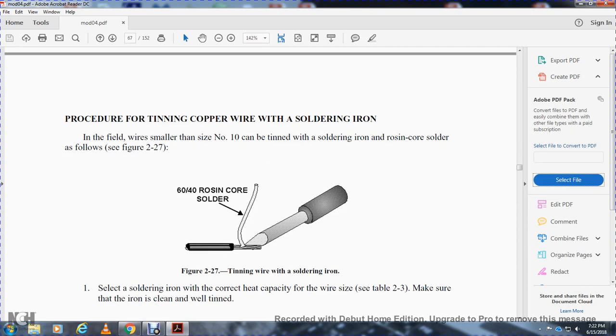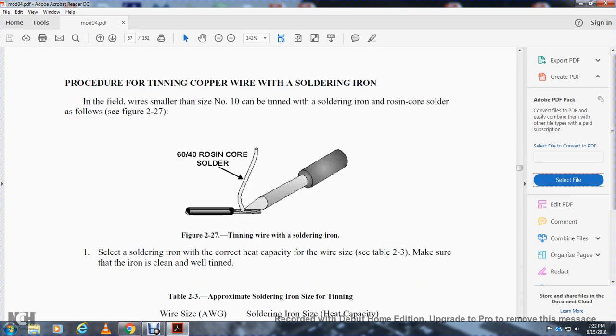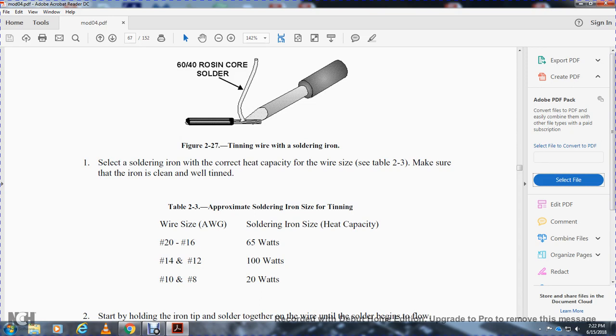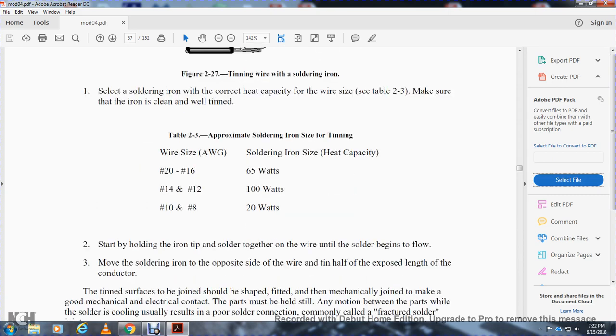Select the soldering iron with the correct heat capacity using the wire size in table 2-3. Make sure that the iron is clean and well tinned. Table 2-3 shows the approximate soldering iron size for tinning. American wire gauge 20 to 16, 65 watts; 14 to 12, 100 watts; and 10 to 8, 20 watts.